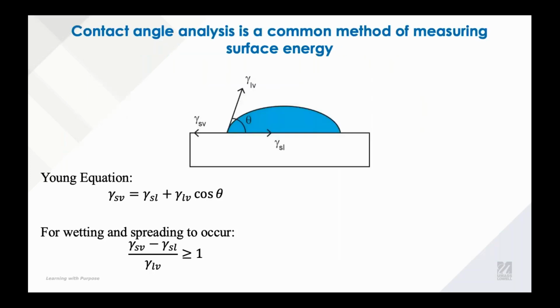Our classical way of characterizing surface free energy is with the sessile drop experiment, where you put a small droplet of a liquid onto a substrate and then measure that contact angle. And Young's equation describes this relationship at the triple point, so at the intersection of our liquid, gas, and solid phase. And this is something that pretty much everyone who's using a contact angle experiment is familiar with. And so we can use the contact angles from either known liquids or known solids in order to be able to determine our surface energies. Next slide.